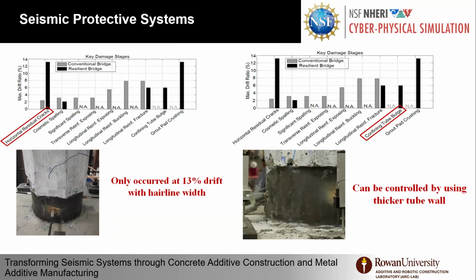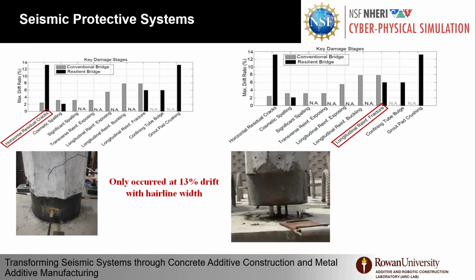It rocked on the surface. The foundation also got some cracks and spalling due to the rocking motion. The steel tube at the end had a bulge due to the high dynamic loading. We also have a big challenge here where, after we saw cut, we actually know that the rebar fractured, from the sound as they fractured during the test.